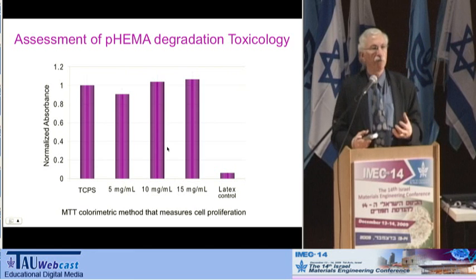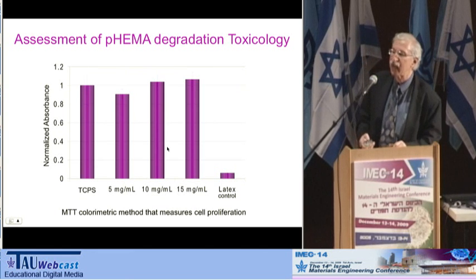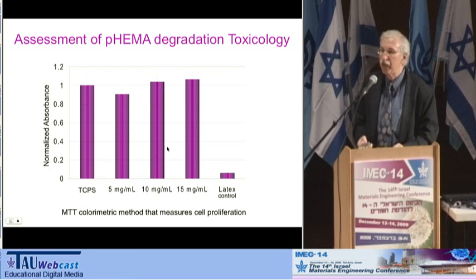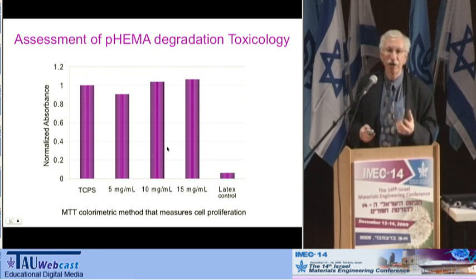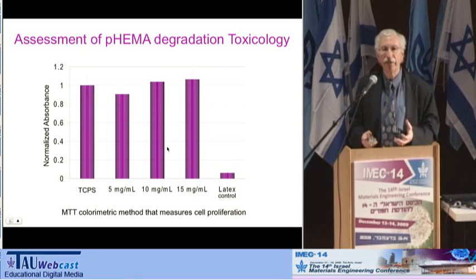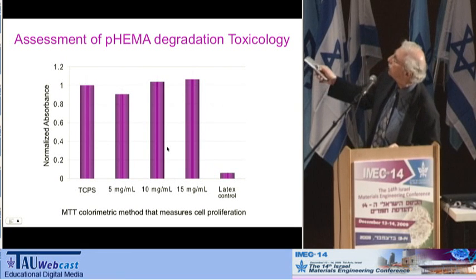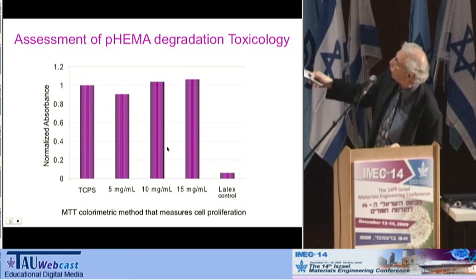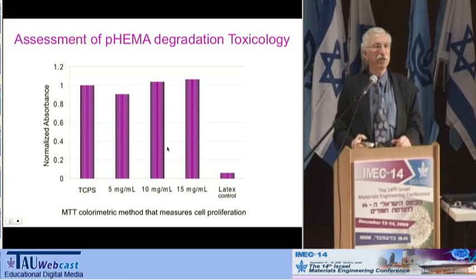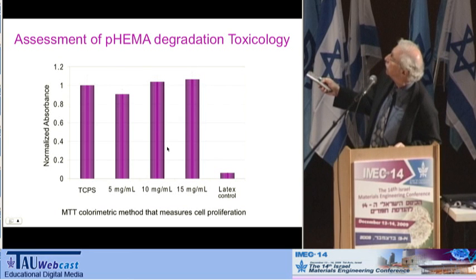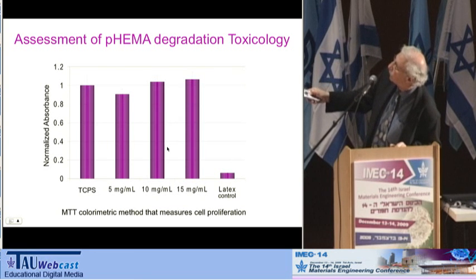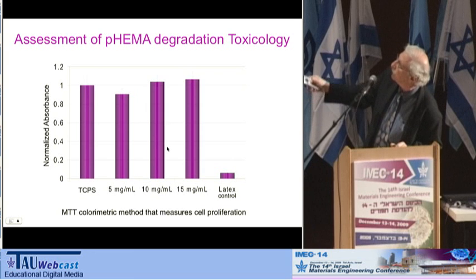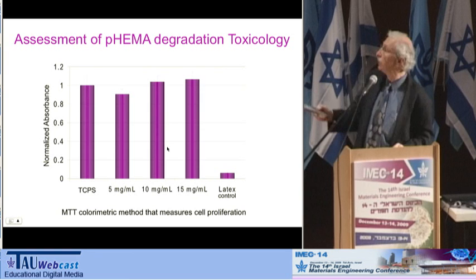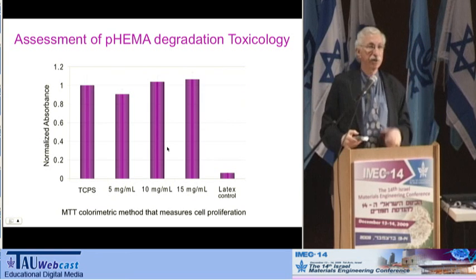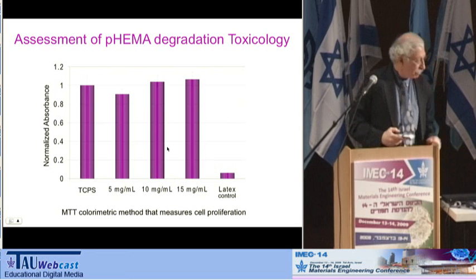Another question is, what about these fragments? Are they toxic? Well, this is an assay for toxicity. Basically, we're using an enzymatic process to make a color change. If the cells are alive, they have this enzyme and they make this color change. So you see this nice color absorbance. Latex is pretty toxic to cells, and we don't get this color change. This is the control, which is tissue culture polystyrene. The cells make plenty of color, and various doses of the degradation product from this have essentially no effect on the cells, so it is not toxic.